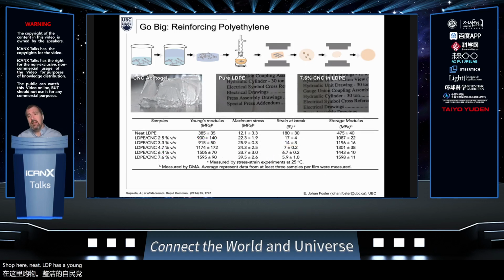Neat LDPE has a Young's modulus of about 400 MPa. With just 7% of our cellulose nanocrystals, we can get up to 1600 MPa, so 1.6 gigapascals. So you can really take a low end, low density polyethylene, and reinforce it with these cellulose nanocrystals. Huge mechanical reinforcement using this. Now, like I said, using this solvent is a multi-step way to get to reinforced polyethylene, not industrially viable. But it shows the possibility that if you do this in the right way, you can get to a reinforced polyethylene. A very low end polymer that you do these tricks with and make it much, much better, kind of into the engineering polymer regime.